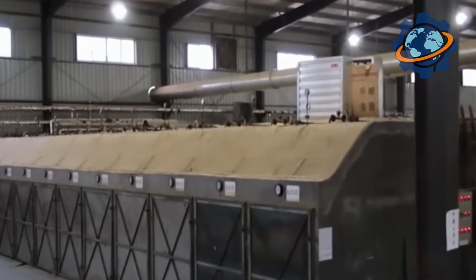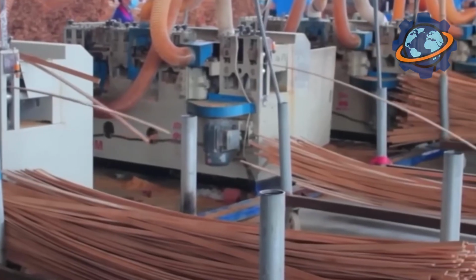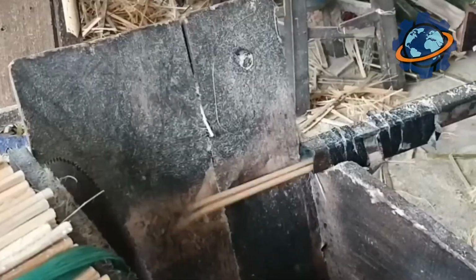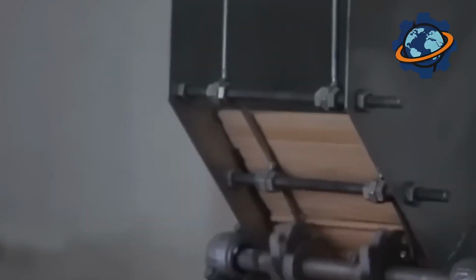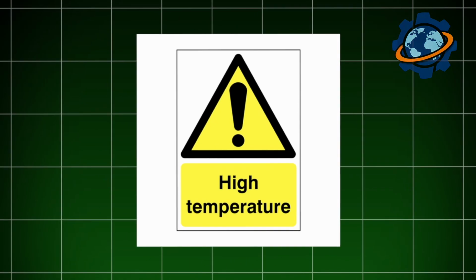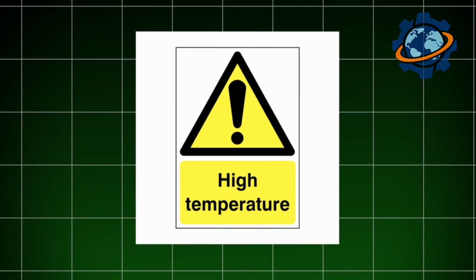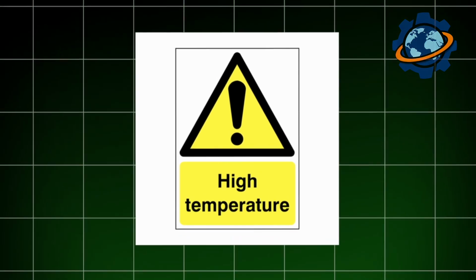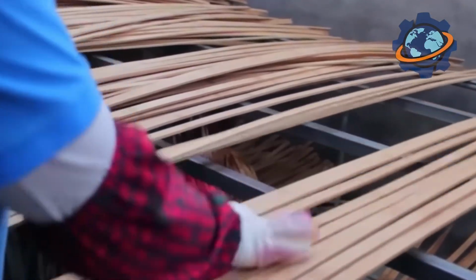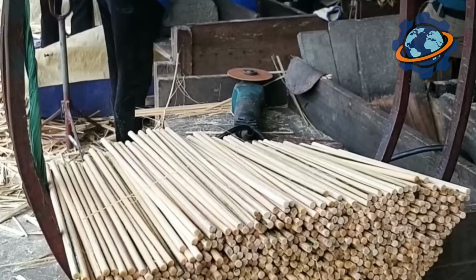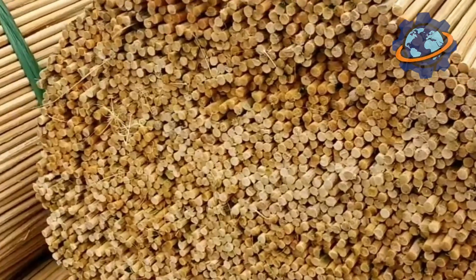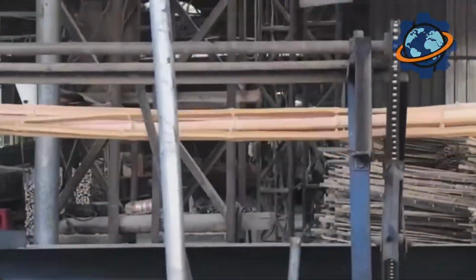Here, the bamboo planks are not just glued together, but completely shredded into long fibers, mixed with an environmentally friendly resin, and loaded into huge steel presses. Under infernal pressure, reaching 3,000 pounds per square inch, and high temperature, this mass transforms into an extremely dense, monolithic block. The hardness of such flooring on the Janka scale can exceed 5,000 units, making it more than 3 times harder than oak, and more resistant to scratches and dents than most traditional wood species.